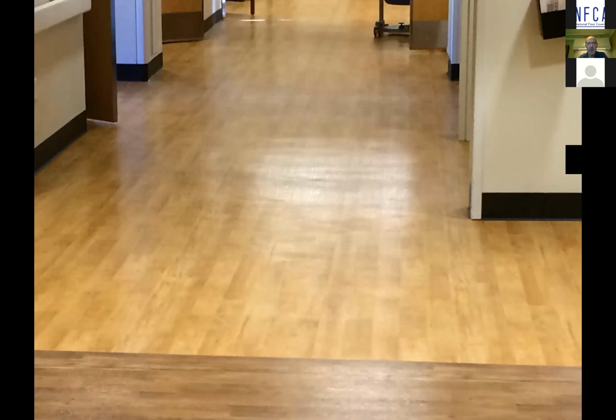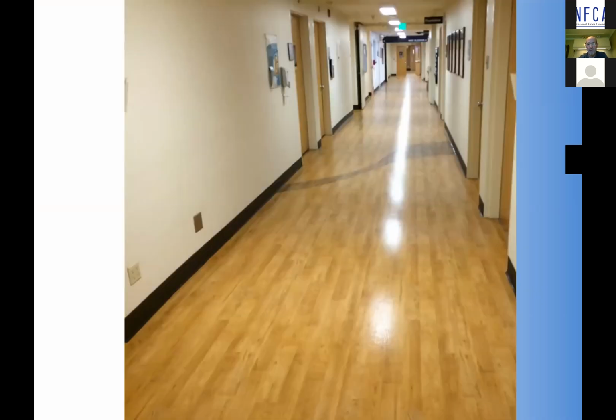So you can imagine you skim, you sand it, and then you skim again, and then you sand it. As good as we can do hand prep, sometimes you'll get these types of optics. So when you're doing thin pour types of self-leveling, you'll get a much truer optic in the surface. But in addition, you'll get truer drying characteristics for your adhesives, and you'll have a better, more consistent canvas, generally speaking. That's not to say that we need to replace patching, but there is new technology now that you can get some pretty smooth floors without having to go through a sanding and hand prep process.